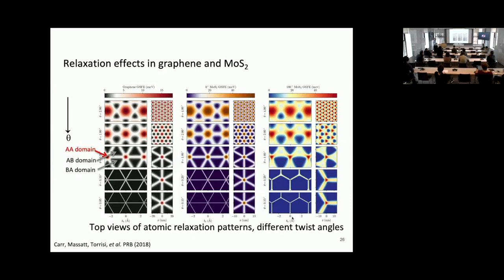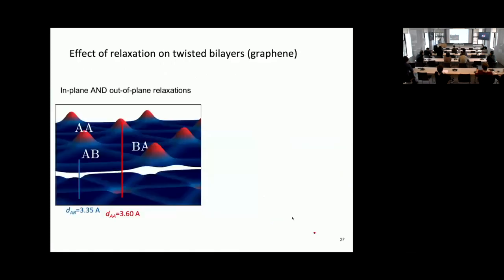It tells you that right at 1 degree, which is the magic angle that we mentioned earlier, the pattern sets in, this relaxation pattern that I was mentioning, and then it doesn't change from then on. Okay. Now, here's another view of this pattern. So this shows you also the relaxation in the vertical axis, which is significant.